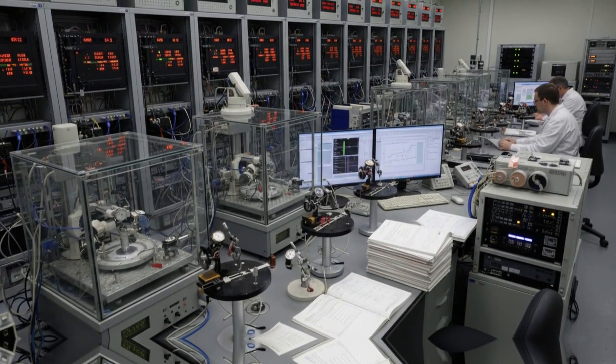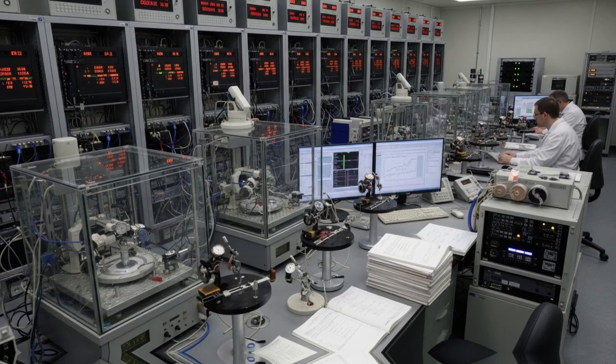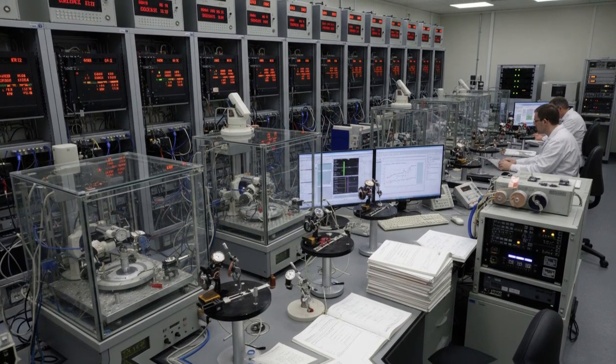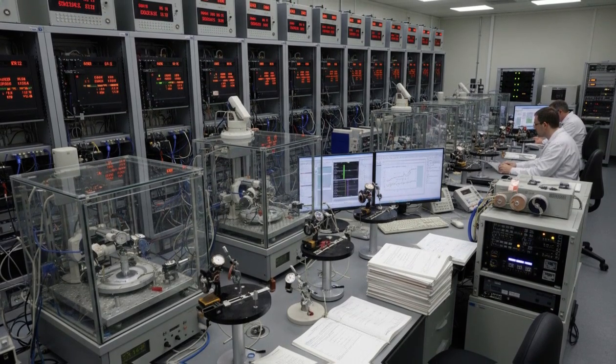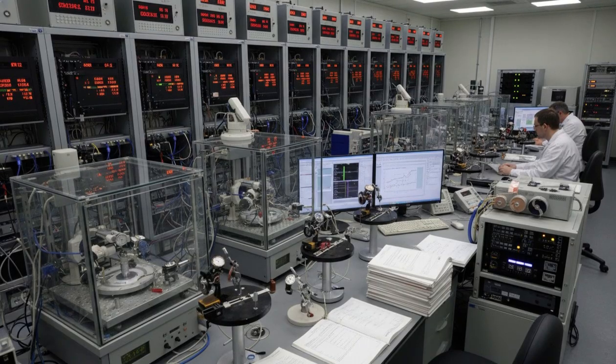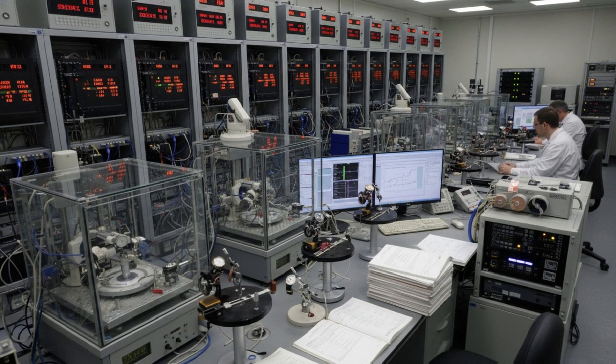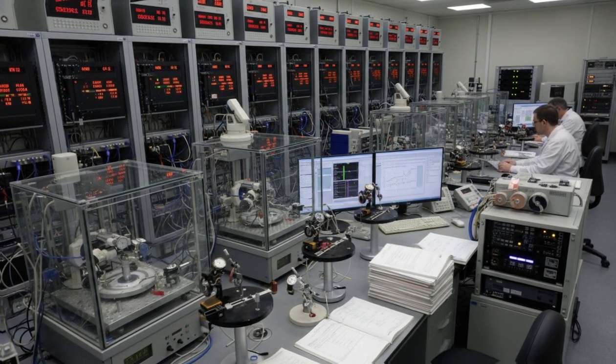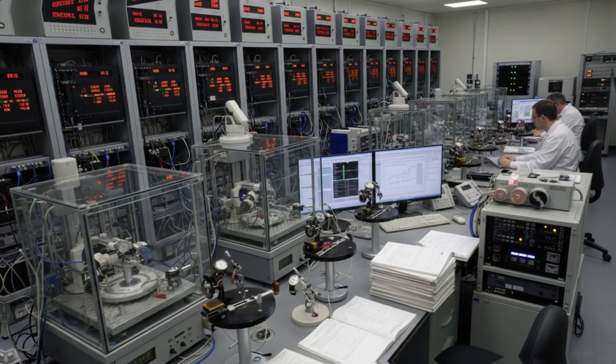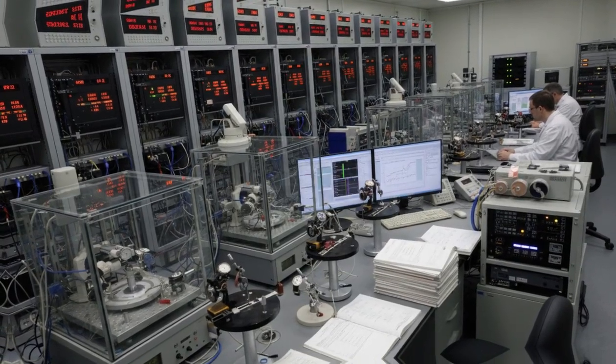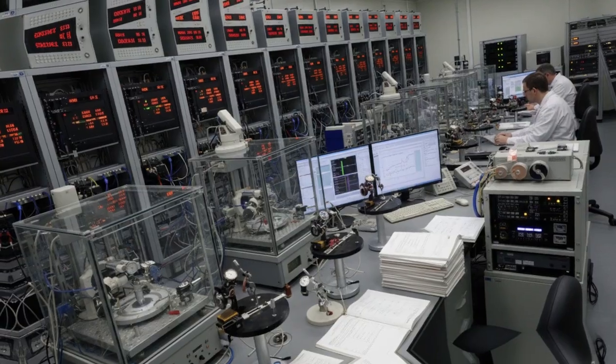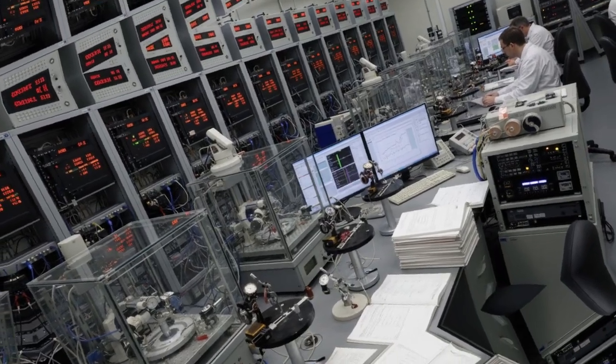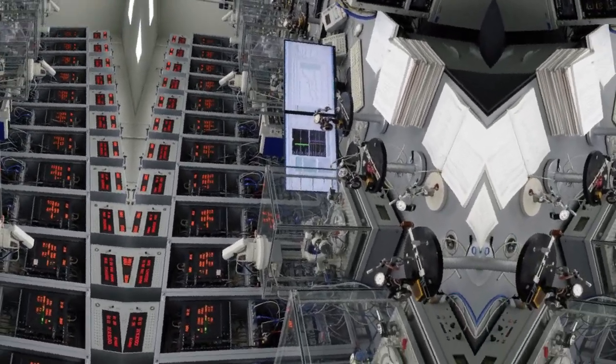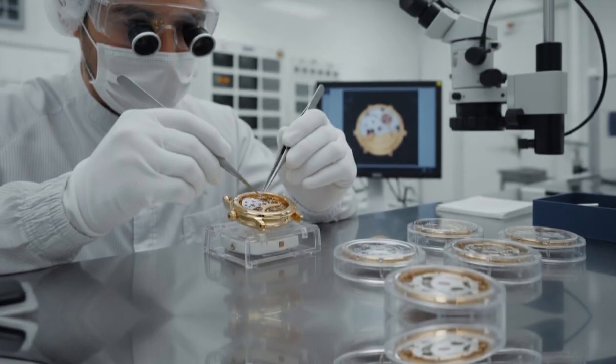Samples are cut from each bar and sent to the analytical laboratory, where they're subjected to spectroscopic analysis, a technique that identifies the exact chemical composition by analyzing how the metal absorbs and emits light. The results must match the target formula within incredibly tight tolerances. If the gold content measures 74.9% instead of the required 75%, the entire batch is rejected and returned to the furnace for reprocessing. This might seem excessive.